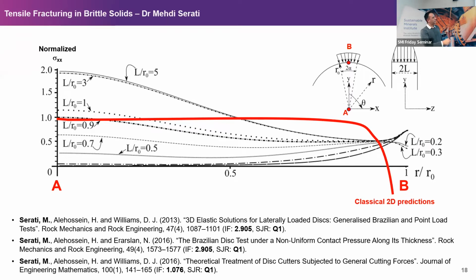If the distribution of load along the thickness is not uniform, look what's happened. The point with the highest tensile stress is not at the center anymore, but it shifts towards the contact area, which is in good agreement with the experimental results. Because in the experimental results, you remember some of the fracturing didn't happen at the center, but rather at the contact. So with this 3D framework, we feel at least we can provide some explanation why the point of crack initiation is not at the center, it moves away from the center.